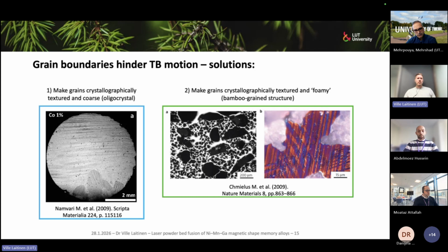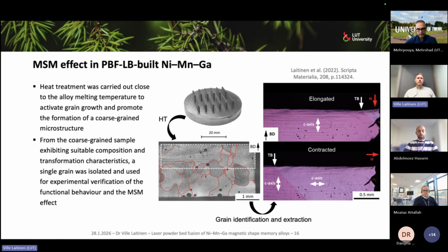And this is what we try to achieve with additive manufacturing. And this is exactly what we did here. So this is where we demonstrated the MSM effect in a laser powder bed fusion built nickel manganese gallium. And we made it by making these very thin walls. And when we do this very high temperature treatment at near solidus temperature, we get this grain coarsening happening.